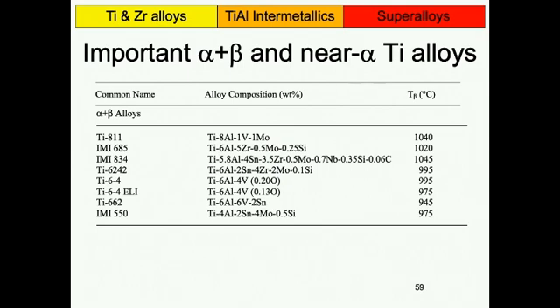Then you have zirconium and tin, and they are neutral elements. They're really added for solid solution strengthening. And then you have the aluminium. So the 6242 and 834, they are very common alloys. In fact, 6242 remains a very common alloy even in modern engines. But yeah, you can see here, so you can draw the line here essentially. Everything above this line, so everything from 6242 upwards, is considered a near alpha titanium alloy. Everything below is more kind of an alpha plus beta titanium alloy.